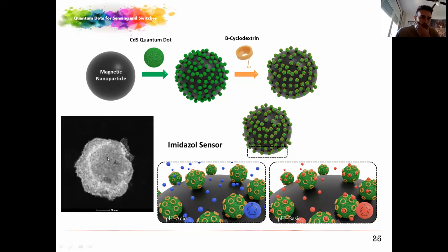This is a real image of a magnetic nanoparticle decorated with quantum dots. I don't know if you can see here the small balls around the whole surface. The drawing is only a representation, but the real situation is full of quantum dots here. It's a very good image.